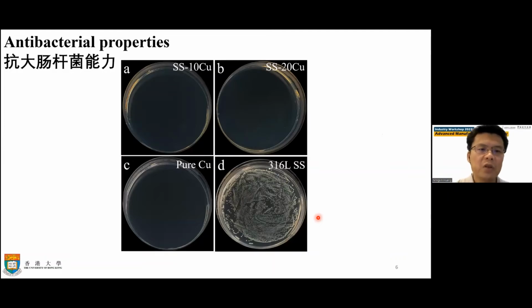And in addition to the antivirus properties, we also check our antibacterial properties. So clearly, pure copper is also very good. You don't see any bacteria here, okay? So this is the stainless steel. After 24 hours, you see a lot of bacteria. So it means normal stainless steel doesn't have this antibacterial property, and also does not have the antivirus properties. But for pure copper, you have the antivirus property. You also have antibacterial properties.